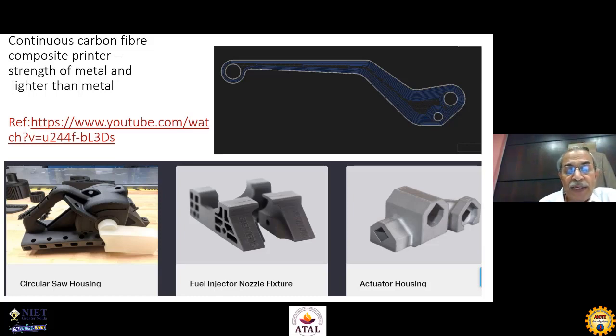If you see the middle one, these are the cavities which have been created. If you see the middle picture, that was actually material which was not needed. And if I create a cavity, I reduce my time of printing, I reduce my weight, and I reduce my material consumption. And by creating these cavities, I also provided an air cushion, which was not possible before. So it effectively improved the reliability of this part much more.